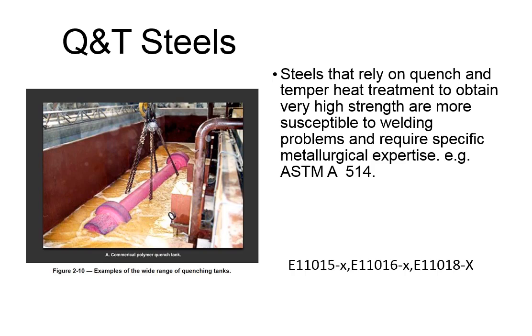Quench and temper steels. Steels that rely on quench and temper heat treatment to obtain a very high strength are more susceptible to welding problems and require specific metallurgical expertise. For example, ASTM A514. I looked up some manufacturers' data sheets on welding ASTM A514. And these are the listed shielded metal arc welding electrodes that are suggested. So we're not just talking about a 90-15 or a 90-16 or a 90-18. We're talking 110-15, 110-16, and 110-18.